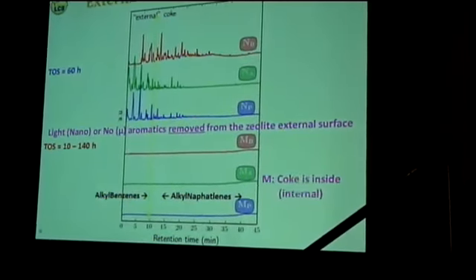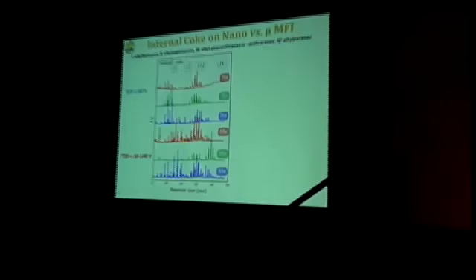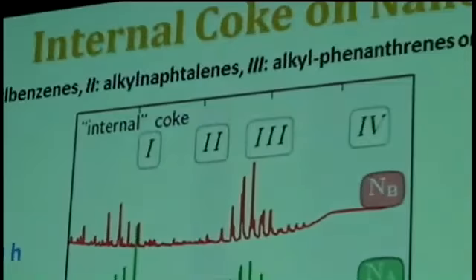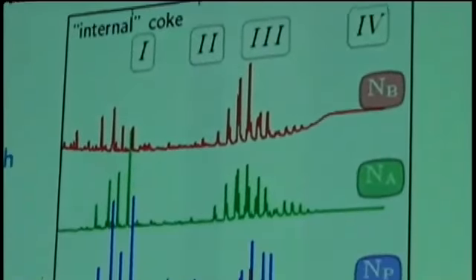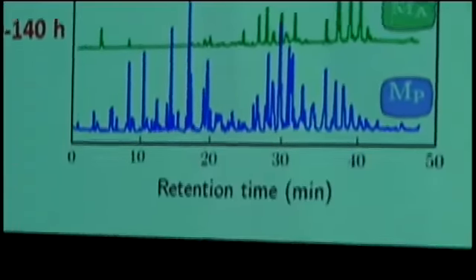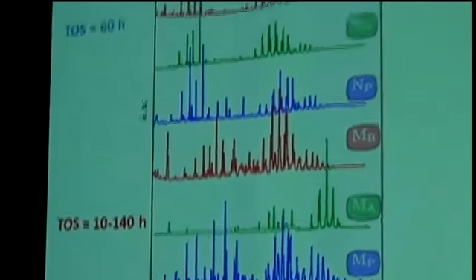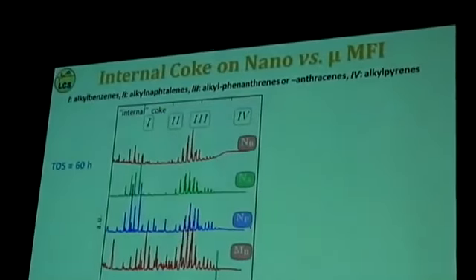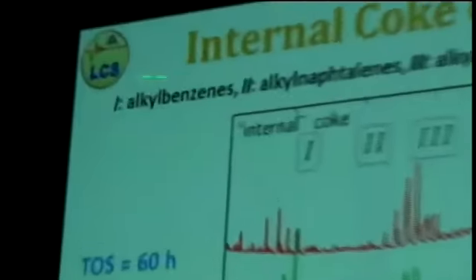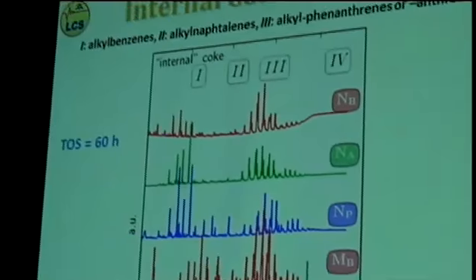Now, if we have a look at the internal coke, we have this picture appearing. So here, for the MA and for the MB, we extended the time, but you see now that inside, after dissolving the zeolite and analyzing all the coke molecules by GCMS, the family of molecules that you see inside is extended. You still see alkyl benzene, alkyl naphthalene, but you start to see phenanthrene, anthracene, and pyrene appearing.